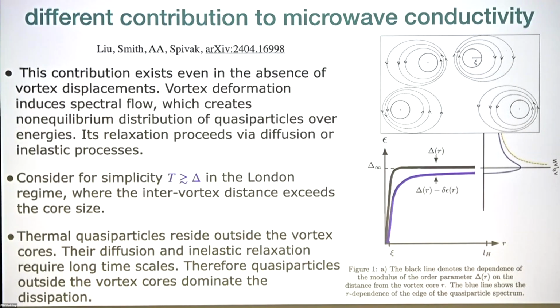But then the threshold of the quasi-particle energy gap is actually suppressed below delta because of the depairing caused by the currents. And so this is the kind of picture on the horizontal line of this density of states. This is the BCS peak, the orange dashed line. And due to depairing, the peak is broadened and the gap is lowered below this threshold. And the main contribution to dissipation will arise from quasi-particles that live outside the core and in this broadening region.